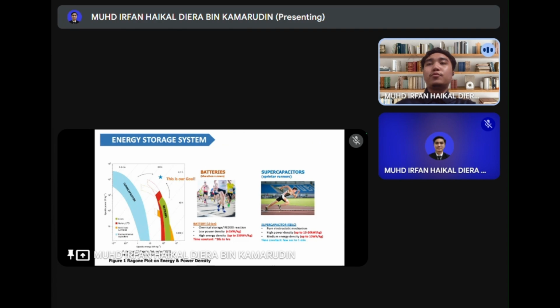So, what exactly is a supercapacitor, and how does it compare to the traditional battery? A lithium-ion battery stores energy chemically through redox reaction, and it offers higher energy density. However, it generally has low power density, so it takes time to charge and discharge. While on the other hand, a supercapacitor stores energy physically through electrostatic charge accumulation. This gives it a very high power density, however, it has a very low energy density compared to a lithium-ion battery. So it stores less energy than a battery of the same size.